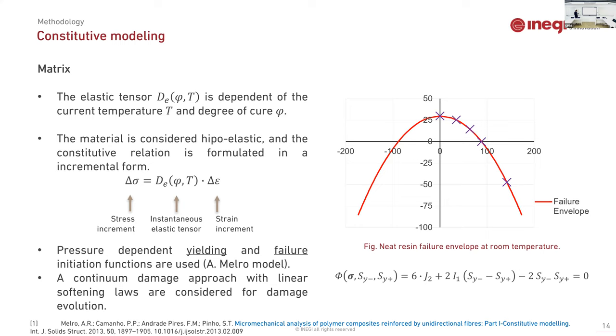This is one of the most relevant parts because, considering this formulation, when the curing process is simulated, this relation will say how the stresses develop during the curing and during the cooling down. Okay. After the curing process has ended, I still have to consider a constitutive model for the resin when it is already cured. And this is a more conventional constitutive model that will consider the same elastic tensor at the condition where the material has ended the curing process. But now I have to include the mechanical features, let's say yielding, failure, and so on.